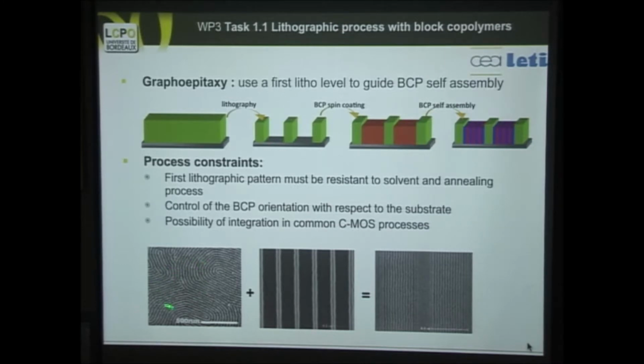I showed you that when you have it on a free surface, then you obtain these pictures that look like fingerprints. However, if you put barriers, like I show here, and this can be done by classical lithography, you take a resin, you make small containers here, you fill with the polymer, you anneal it to reveal these microstructures, and then they orient in a particular way, either parallel or perpendicular, depending on the structure. This phenomenon we call graphoepitaxy. This is a Greek word, but you understand the meaning, for the solid state chemists and physicists.